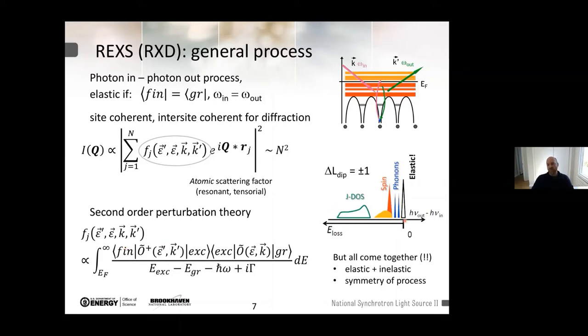So what you get out in reality, in terms of energy loss out of your sample when you impinge with photons, is, apart from electrons and other things that we are not considering, a bunch of photons. And some of them have lost energy because they talk with available degrees of freedom in matter. And this is the pertinence of inelastic techniques. Instead, we are only dealing with the elastic part, the one that comes out with exactly the same energy or very, very close to the impinging photons. The problem is that it's sometimes difficult to separate this part out of everything else.